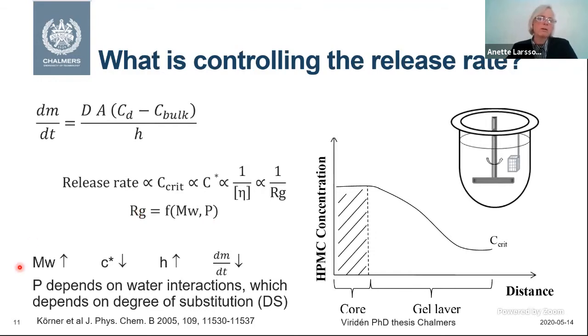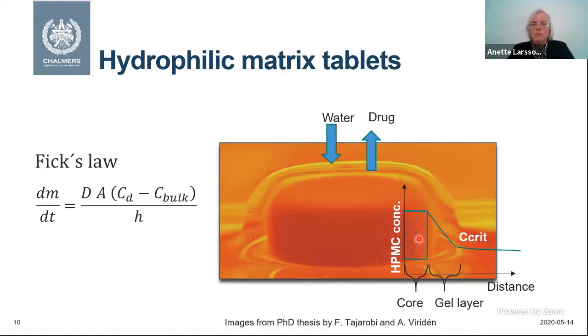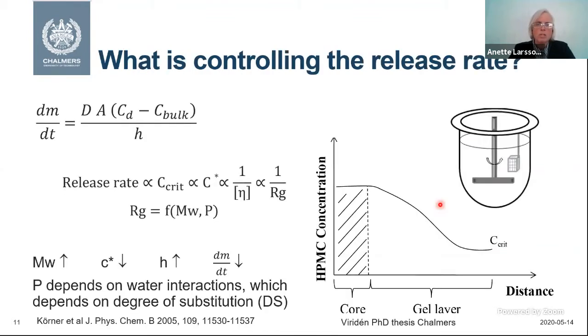So if we increase the molecular weight, then the overlap concentration will decrease. And if we decrease the overlap concentration, then more water needs to be transported into the gel. So if we go back here, more water needs to go in here and dilute the gel more and more, which means that you have a larger gel layer and a longer diffusion length there, which then slows down the drug release rate or the water transport rate.